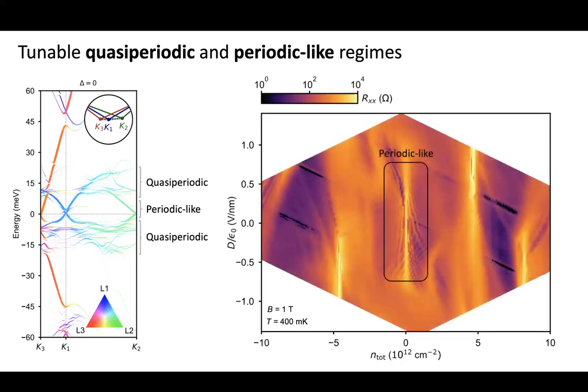If you look near charge neutrality, where you have these three sets of quantum oscillations clearly resolved, that's because the electrons there think they are in a periodic system with three Dirac cones with renormalized Fermi velocities. When you go outside that region, the quantum oscillations disappear because you're in the spaghetti flat bands now, except one, which can still be seen a little bit, which is the fast band, which still maintains a little bit of its periodic-like character.